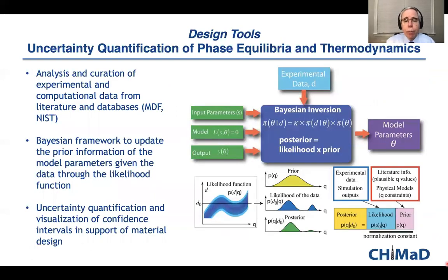The uncertainty quantification is a very important part of the center, because when you're designing material, you have to know the uncertainty associated with predictions from a simulation or uncertainties associated with the experimental data and how that propagates down the line with your designs, and how much uncertainty you have in the end design of your material. And so this is using Bayesian frameworks that allow us to use the uncertainty in experimental data to understand the uncertainty in the model parameters. And it's very easy to use this in a cyclical way where you can come back and modify the Bayesian method to understand exactly what the model parameters are and their uncertainty. This is a new group that's become very important in the past couple of years since we started in the second iteration of the CHiMaD.